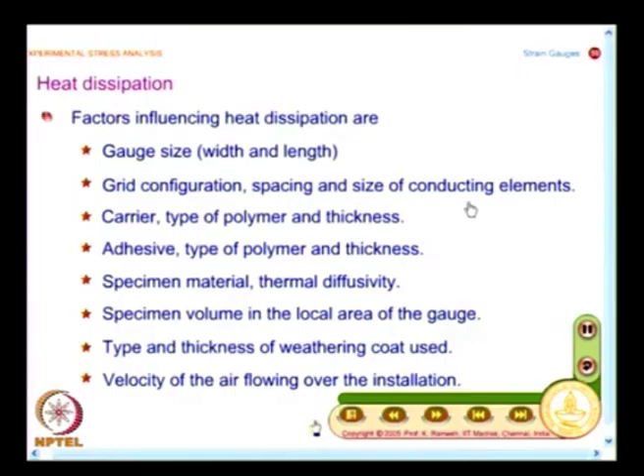See, when you say the configuration, I had already mentioned I can have a rosette with strain gauges separately aligned, and I can also have them as stacked. And from measurement point of view, the approximations involved in idealizing the point on which you make the measurement, stacked rosettes are better. But stacked rosettes bring in another problem. The heat generation will be much more in a stacked rosette than the normal rectangular rosette, where they are kept slightly away from the point of interest. They meet at a point of interest, they are not exactly on the point of interest for which you want to make the strain measurement.